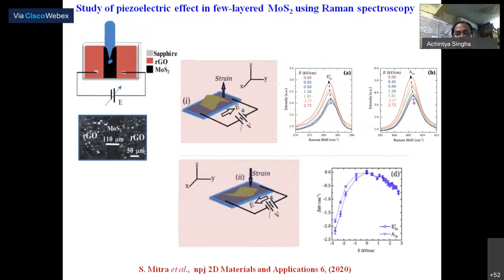If you reverse the electric field, then the strain will be in the opposite direction, and since the material is on top of the substrate, the strain effect in the opposite direction is lower than the strain effect in the previous direction. As a result, we can see that the shift in this configuration is much lower than in the other direction. You can see on the right side the delta omega change for the positive and negative direction of the electric field. So with this experiment, I want to give you the message that we can measure the piezoelectric properties of this material using Raman spectroscopy, and this paper has recently been published in npj 2D Materials and Applications. Okay, go next.